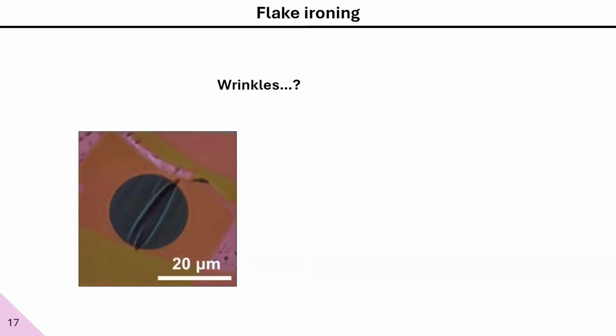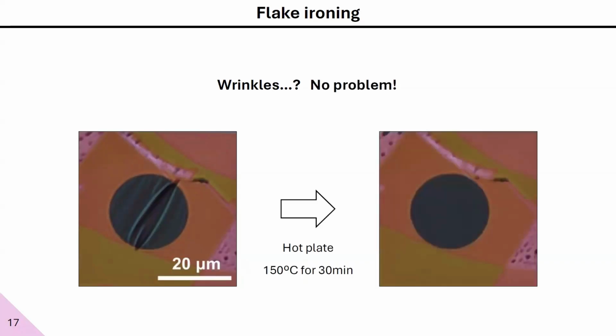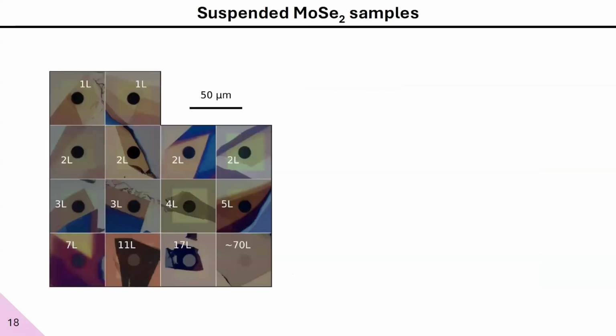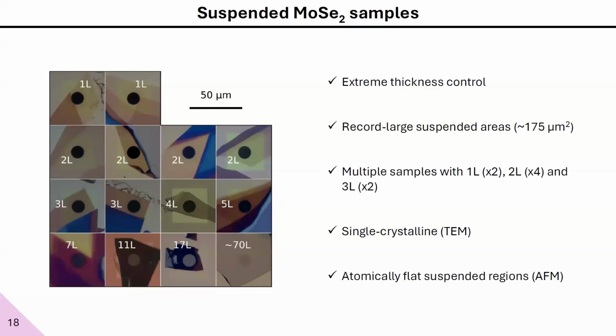What happens is that sometimes they become wrinkled. Luckily, we found out by a simple annealing process that we can flatten these materials and recover their atomically perfect and flat surfaces. So we made several 2D materials, and these samples have, first of all, extreme thickness control. They show record large suspended areas, specifically for our monolayer flakes. These are sub-nanometer thin flakes suspended over 15 micrometer holes. So basically, huge suspended areas of atomically thin materials.